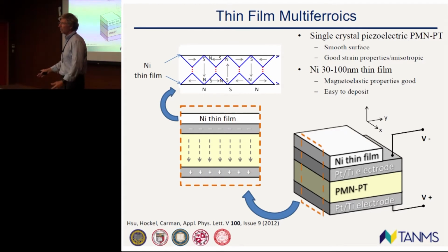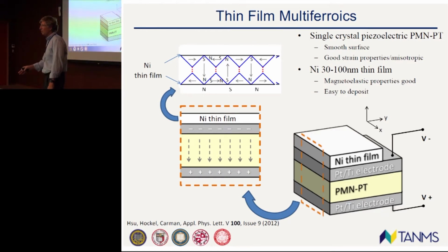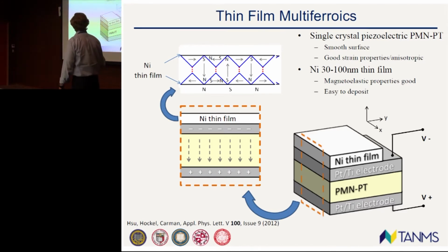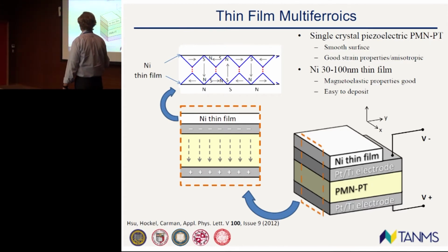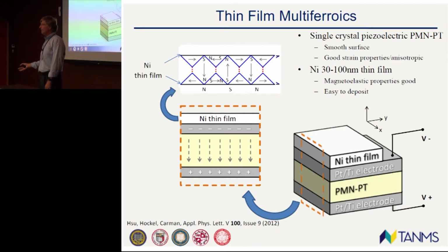It's single crystal. It has very smooth surface. Surface roughness is your enemy when you start getting down to small scale, right? Because what happens? Pinning of domain sites, pinning of spin states. And most of the work you're going to see today, in fact, all of it's going to be in nickel film. Now, why did we choose nickel film? It's just easy. Is it the best material? No. But remember I told you about that first sonar transducer? Do you know what it was made out of? Nickel. It's a decent magneto-elastic material. No, it's not the best. But it does work, and it's simple to put down.